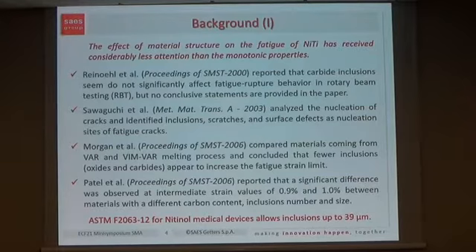But most work was dedicated to the study of monotonic properties. Relatively few works were done at the time in understanding the effect of inclusions, but without any systematic approach and without clear, comprehensive study and conclusions. Also, the regulations used especially for NiTi for medical devices allow inclusions up to 39 microns, but this measure is carried out typically at the semi-finished products. That means that at the end, on stents, on fine wires, and so on, the maximum inclusion size is unknown.